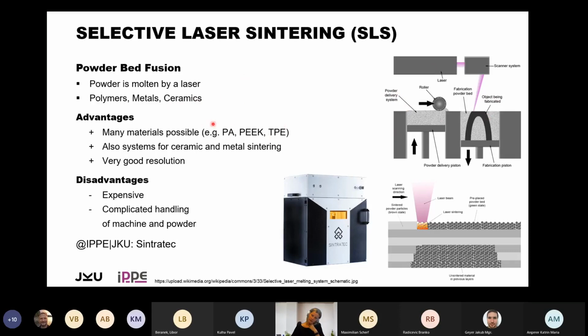And from the polymer side, the options most commonly used are polyamide, polyether ether ketone, and also elastic materials. This is thermoplastic elastomer, usually thermoplastic polyurethane. And the resolution is usually better when compared to fused filament fabrication. The disadvantage is it's more expensive. It's a lot more complicated in handling, as we heard before, with the protective gear. And we have only a small selective laser sinterer in the lab from the company Sintratec.